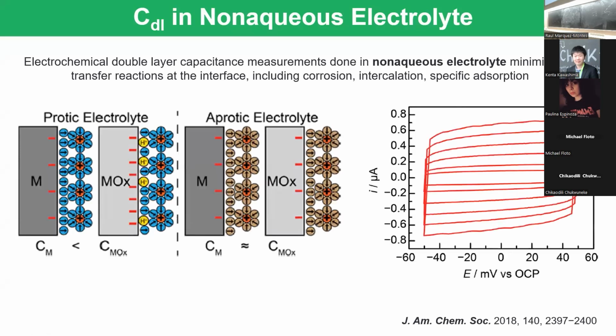Okay, what I'm showing here is a really cool paper about explaining double layer capacitance measurement. So, last consideration: water is not an ideal solvent. Why? Because with water, as you can see in this part here, you have, for instance, proton intercalation. Also, when you work with water, you may have some corrosion problems, like if you immerse a metal in solution, maybe the material is going to start corroding.